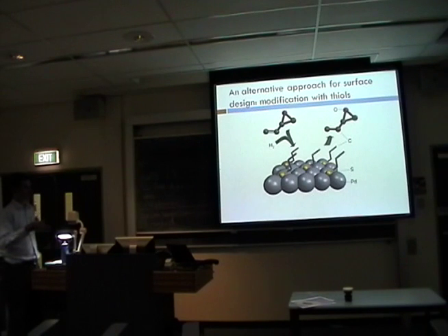And so I'll show a couple of examples of this where we're trying to take an oxygenated molecule, so there's an example here, and modify the surface with very crude enzyme mimics in a way, right, that are organic molecules. In this case we're using a self-assembled monolayer of organic molecules that are tethered by a thiol functional group in order to modify the reactivity toward oxygenated molecules. All right, and for this very simple probe reaction, what we're interested in is simply hydrogenating this carbon-carbon double bond. As you can see here, we're fully saturating it, but leaving this epoxide function alone, which is actually a very difficult thing to do, and something that they're still struggling with industrially, because the oxide is so ring-strained, it really likes to pop open, reacts at very low temperature.